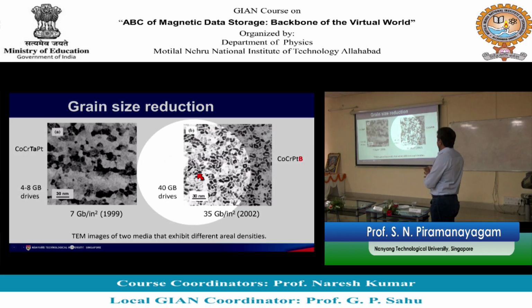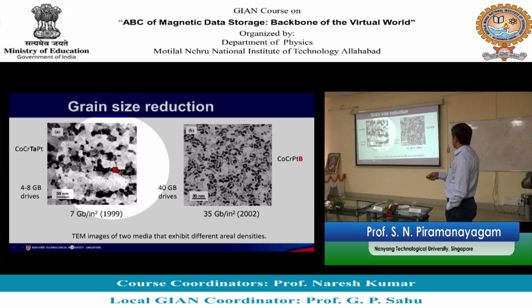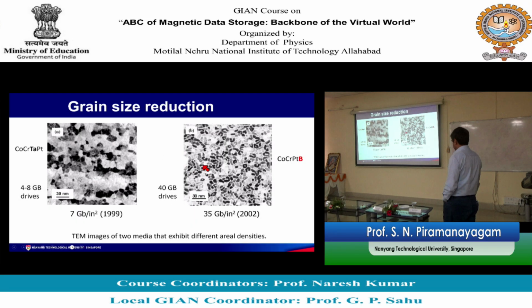So, this is one example of the growth or reduction in the grain size. For example, in 1999, when the areal density was 7 gigabit per square inch, the grains look like this. And when we move to 2002, and the areal density is like 35 gigabit per square inch, you can see the grains are much smaller, right? Compared to this, the grains are smaller.